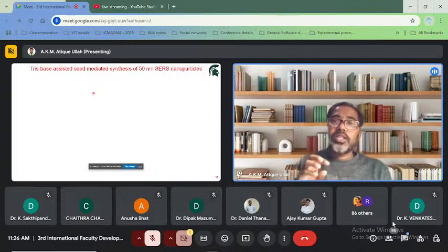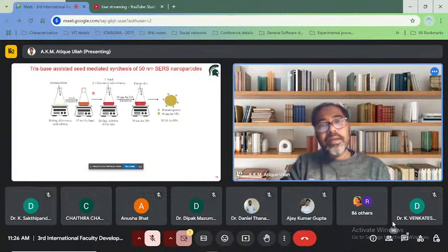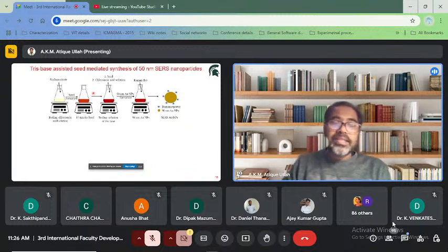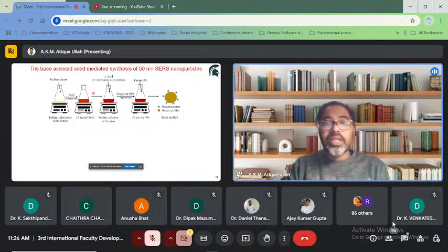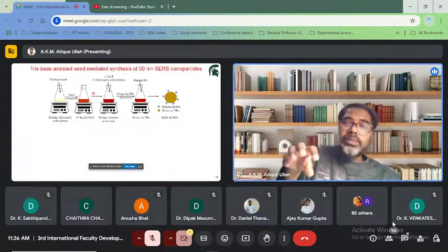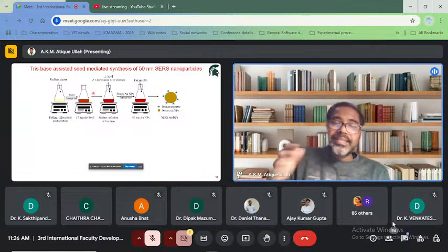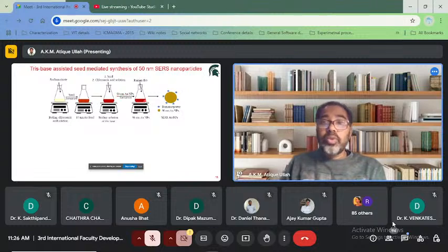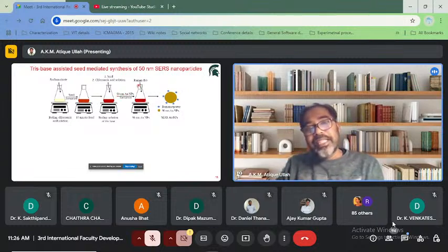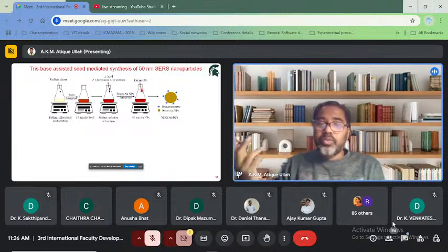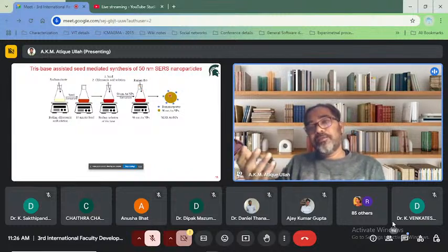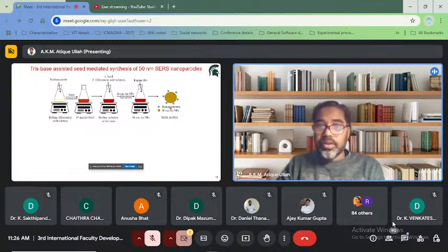Then we synthesize these SERS nanoparticles. Already I mentioned that the 50 nanometer gold nanoparticles, when functionalized with the SERS reporter molecules, we term SERS nanoparticles. I have mentioned in my previous slides how we synthesize the 50 nanometer gold nanoparticles. This is also a one-pot method. That means when we are synthesizing the 50 nanometer gold nanoparticles, we can add a micromolar level of the dye solution. We let it sit for 1 minute, and in 1 minute we find that the SERS nanoparticles are formed.